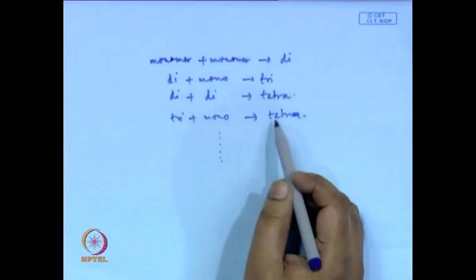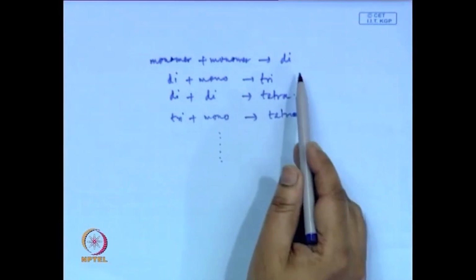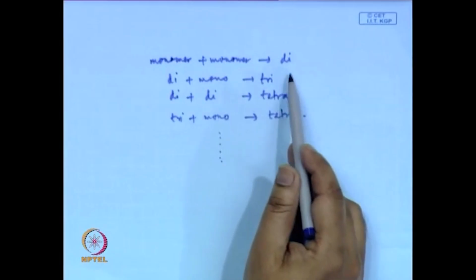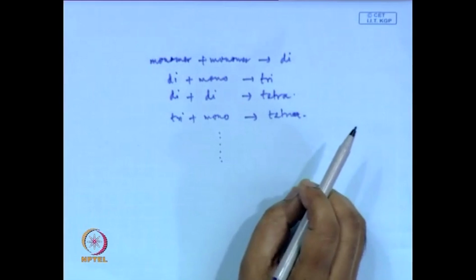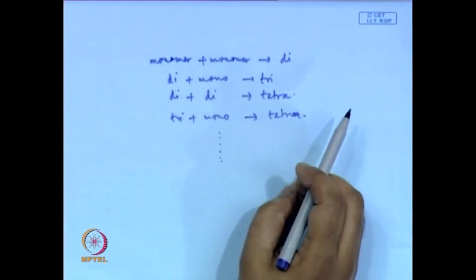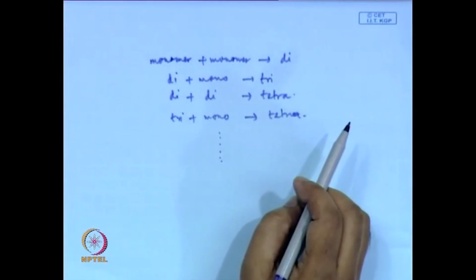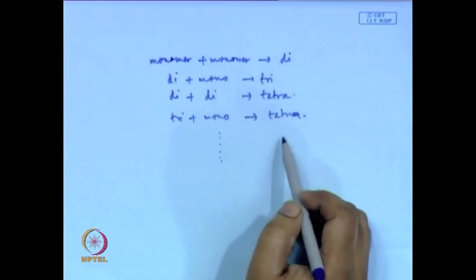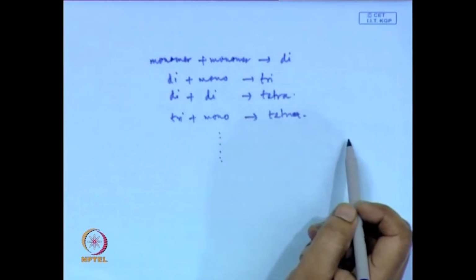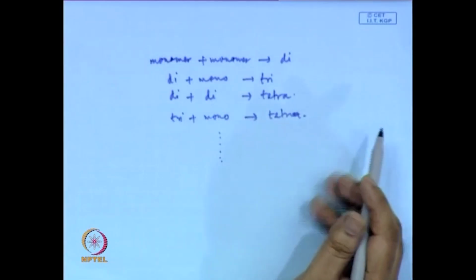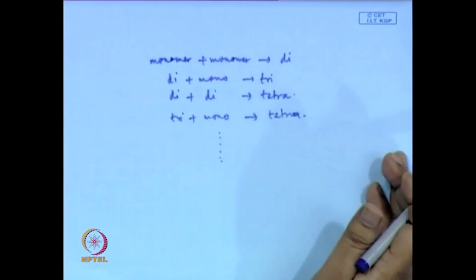In step growth polymerization, if you stop in between, you will see small molecules called oligomers, and a small amount of monomer, depending on the stage at which you stopped. The high molecular weight polymers in step growth only form at the very late stage of the polymerization process.